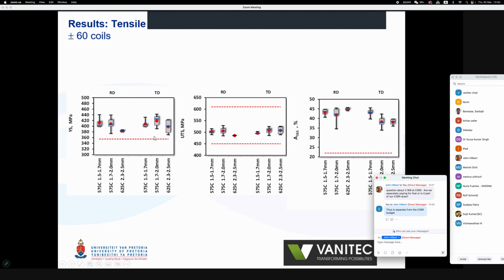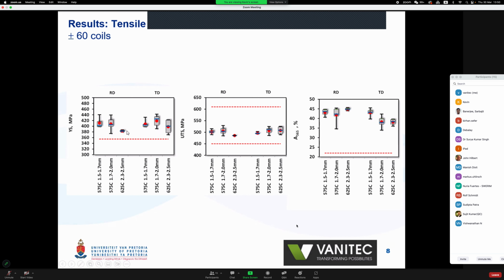The red lines are the max or min of that S355MH spec I was telling you about. You can see RD standing for rolling direction, TD transverse direction. The yield strengths in both directions are fairly similar and fairly isotropic. However, that's for 575 Celsius. As you increase the coil temperature, there's a distinct drop in strength. That was a fairly significant finding, probably related to the size distribution of vanadium nitride, carbonitride.